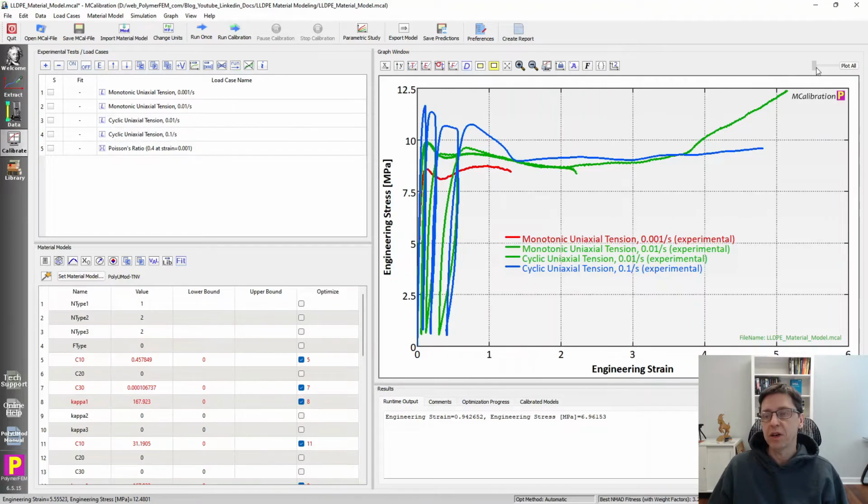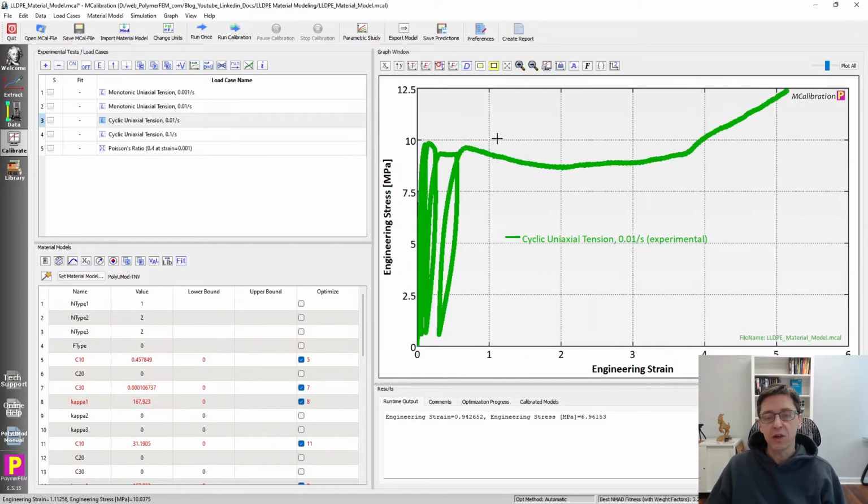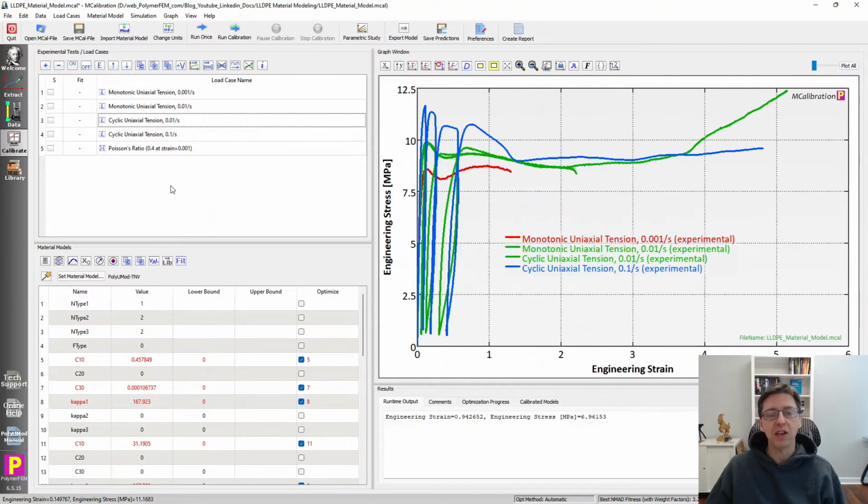And if we zoom in a little bit to each of these, you see the two monotonic tests are pretty standard. It goes up to a yield stress and then they're almost flat. The engineering stress, that is, slightly goes down after yield, indicating a yielding kind of response. And then during cyclic loading, we have significant relaxation. This is linear low-density polyethylene, after all. It's very viscous in its nature. And we'll see we have both stress relaxation and cyclic behavior as part of the data set that we use